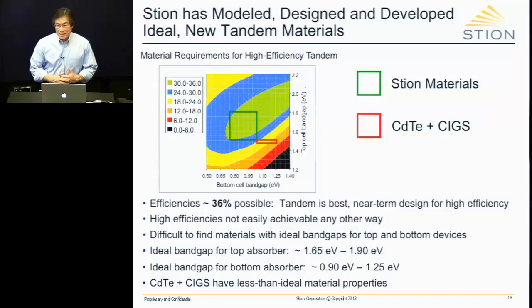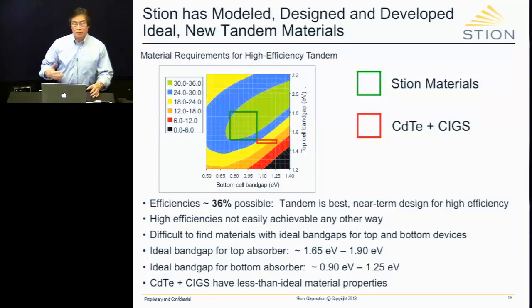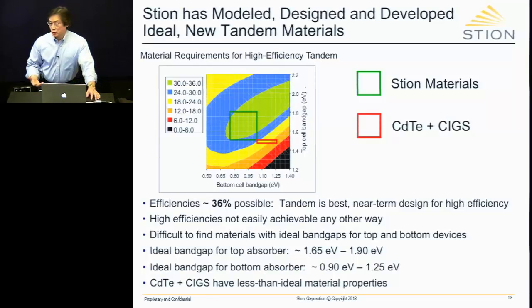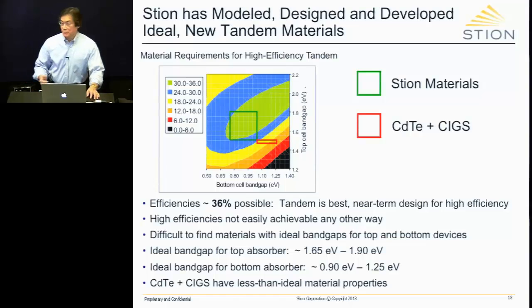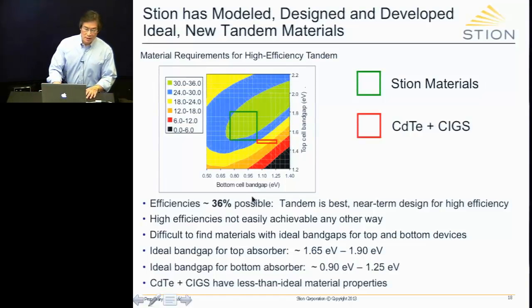So of course, in a tandem, as in any multi-junction device, one of the most important layers is the absorber. And one of the more important aspects of the properties of the absorber happens to be the band gap. What should the band gaps be? So in this case, we did a calculation based on finite difference time domain calculation, FDTD, which are very, very good, actually. And what we've plotted here are those results.